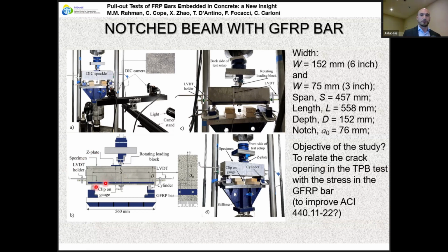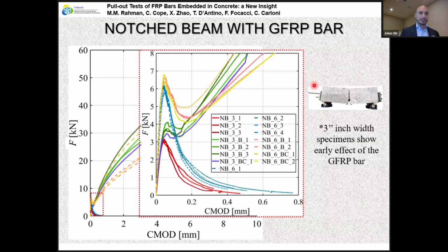We use two different widths of the beam, but the same depth and the same length. And you can see here the results. This is the load versus the opening of the crack. I'm going to zoom in. This is the very first part. The responses that go down, softening, are the ones of plain concrete, no bar. And you can see that the bar starts to pick up the load as soon as you have the initial peak load of the plain concrete. And the difference between the two sets of tests is the difference in the width of the concrete beam.